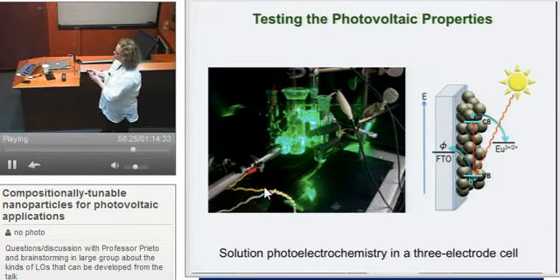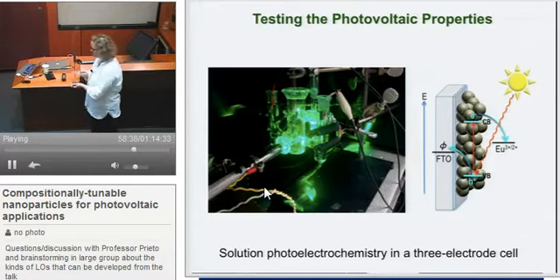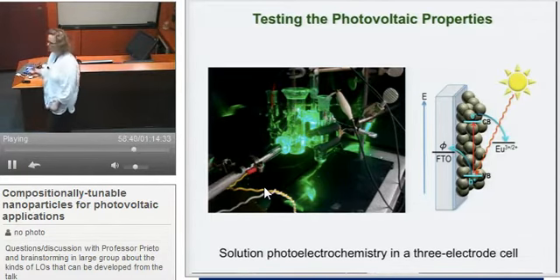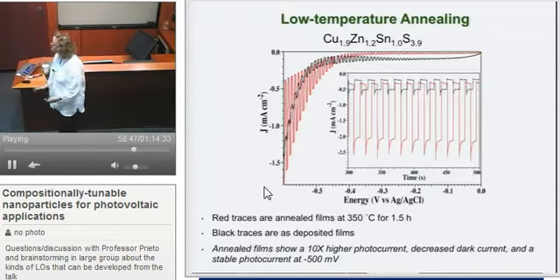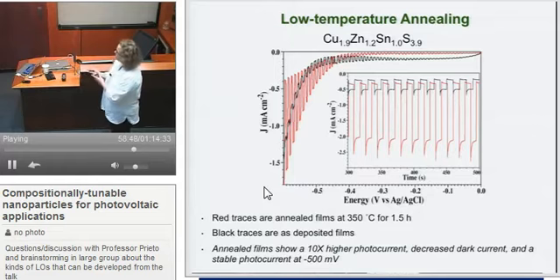So we use a simple 3-electrode cell. This is the little alligator clip, and the little film is here. We have a reference electrode, so we know what potential we're referencing to, and a counter electrode. We use either green light, because it's the middle of the visible spectrum, or a white lamp that mimics the solar spectrum, and we can count how many photons are hitting our sample. So when we do that, the black is the as-deposited film.